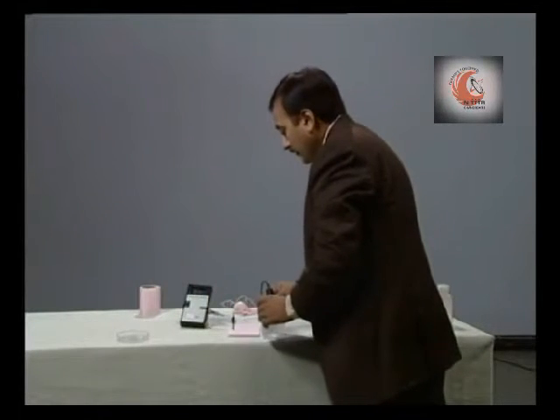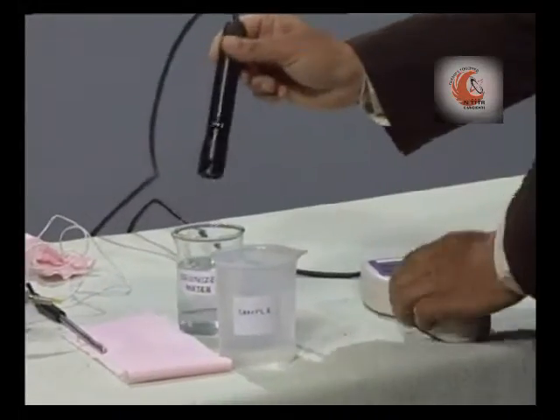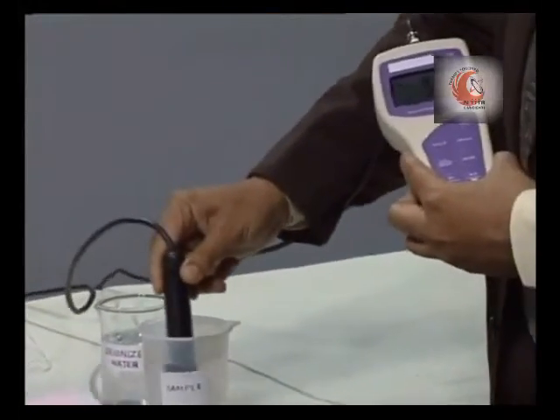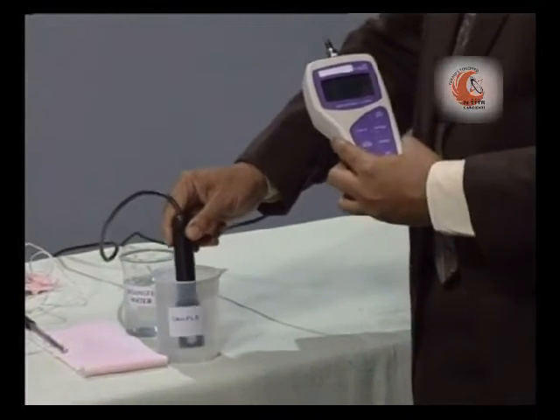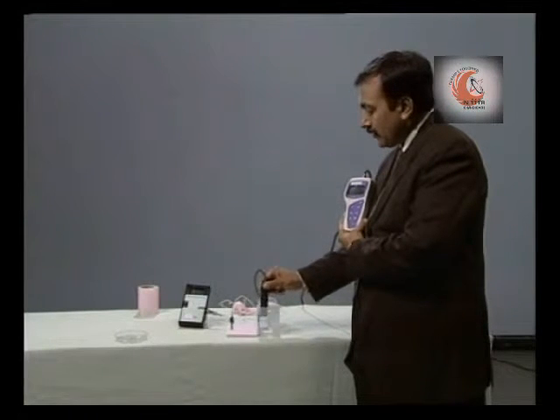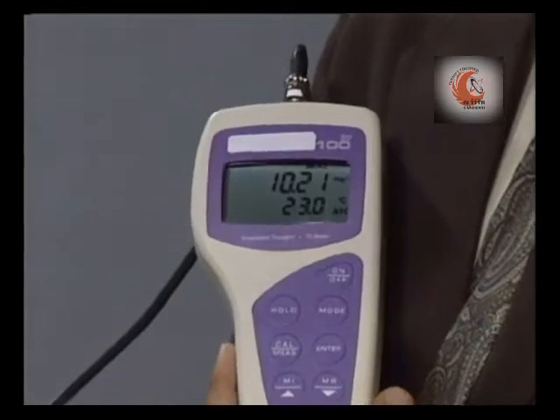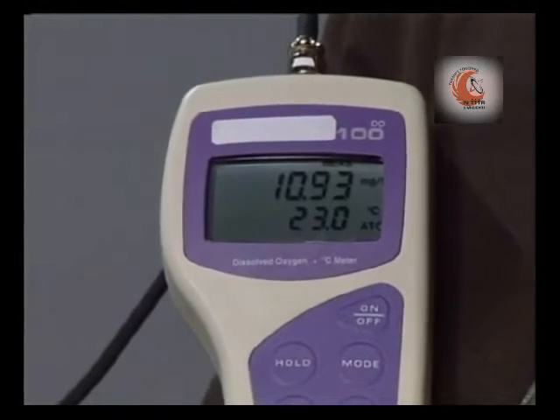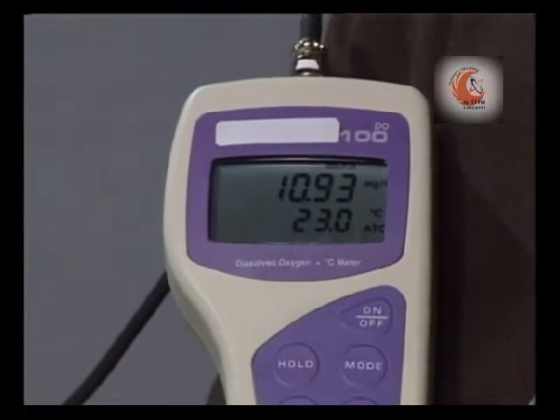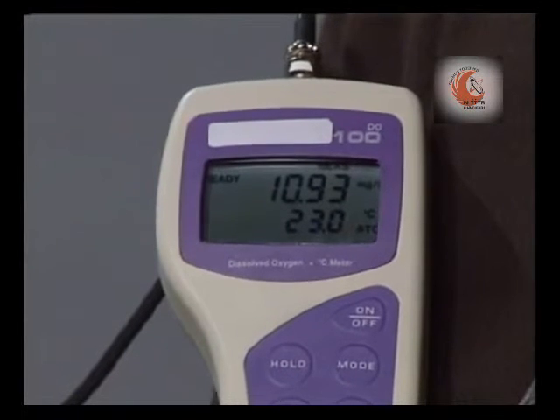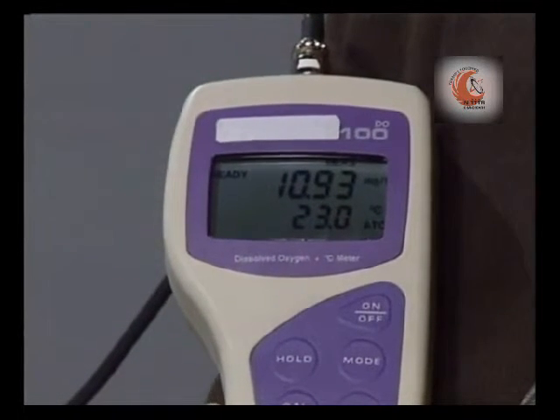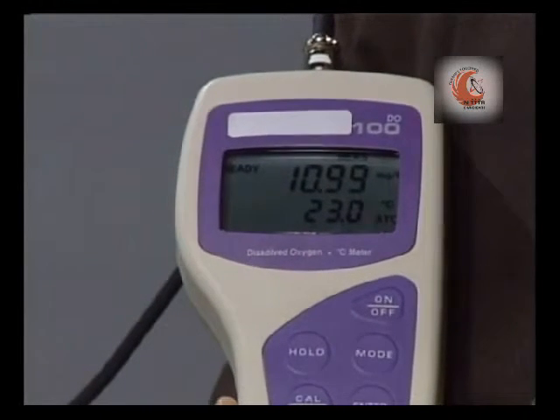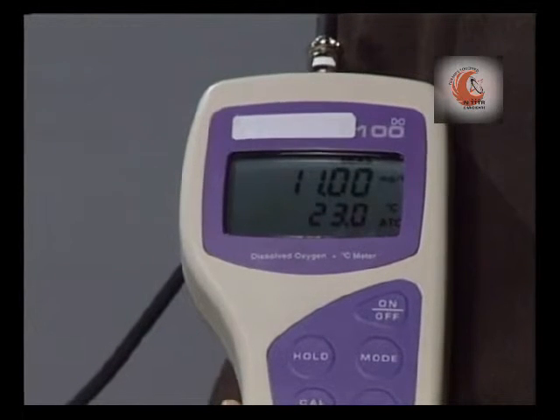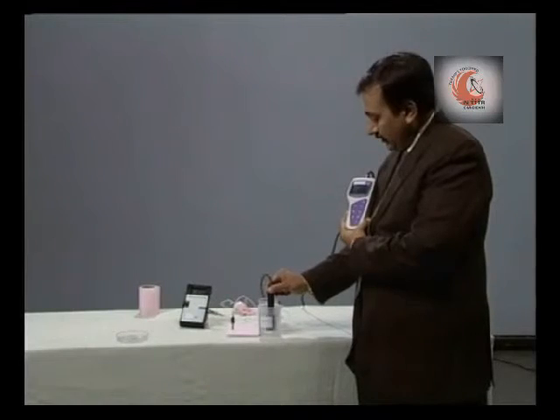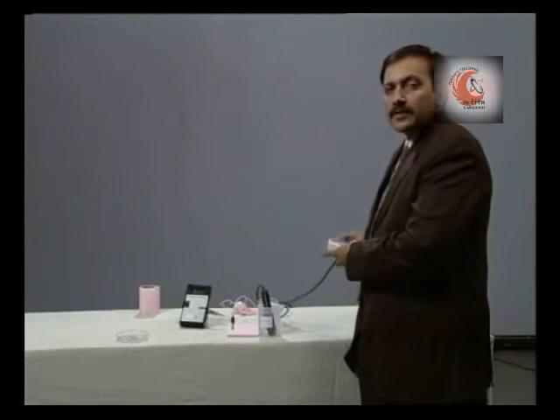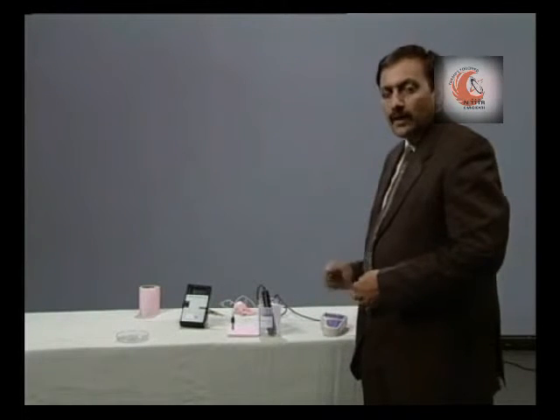So simply put the electrode into the sample and check that the instrument is in measurement mode. Gently stir the electrode, and when the reading is stable, we shall note down that value. So, the ready annunciator is displayed against a value of 11.00. So, we can say that the dissolved oxygen of this sample is 11.00.